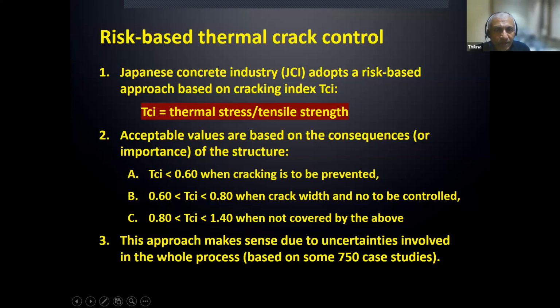Risk-based thermal crack control. The Japanese spend money on research, and they like concrete too. So what they did was a very smart idea. Uncertainty is always involved. So they said, if you do a concrete work, come up with the risk-based thermal cracking potential. So we calculate thermal stresses by the process I gave you, then tensile strength gain by maturity, calculate that ratio, and then say, depending on the importance of your structure, make sure that your cracking potential remains within those numbers. So TCI, thermal stress over tensile strength, should be less than 0.6 when cracking is to be prevented. I have to be very careful: concrete cracks, but it's a calculated, prevented risk. This approach makes sense because we are dealing with uncertainties.